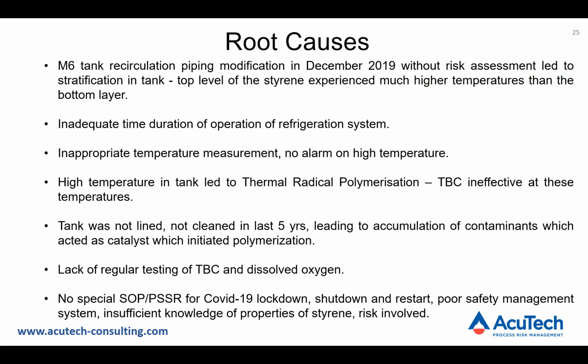Also, the lack of TBC and dissolved oxygen monitoring, lack of procedures for maintaining the styrene inventory during the COVID-19 lockdown, which stopped receipts and transfer of styrene from the tank. Under normal conditions, there was sufficient tank turnover to minimize polymerization due to mixing and TBC level. No special provisions were made for maintaining the tank contents during the lockdown period.